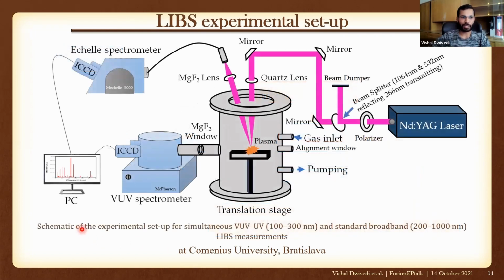This is the schematic of the experimental setup for simultaneous measurement in the VUV, UV and also NIR range, so from 100 nanometer till 1000 nanometer. Here we have the vacuum chamber. The laser beam goes through this path to the inside of the chamber, and plasma is collected simultaneously through 2 paths. One is here to the Echelle spectrometer, and another through the magnesium fluoride window to the vacuum UV spectrometer.